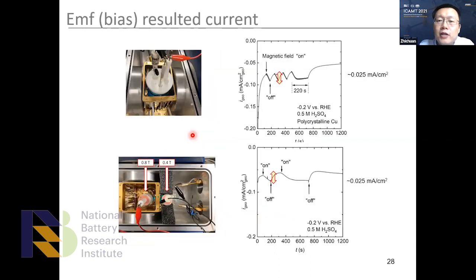Right? So then we do a control experiment again. You can see that no matter where you place your other two electrodes, the reference electrode and counter electrode, whether you place them in the magnetic tip or outside the magnetic tip, you are always changing the magnetic flux within the circuit. So it's independent of the location where you place them. So you can always see the bias induced by this magnetic flux change. Okay, this is the number that changed. You can see that's roughly 0.025 milliampere per centimeter square.